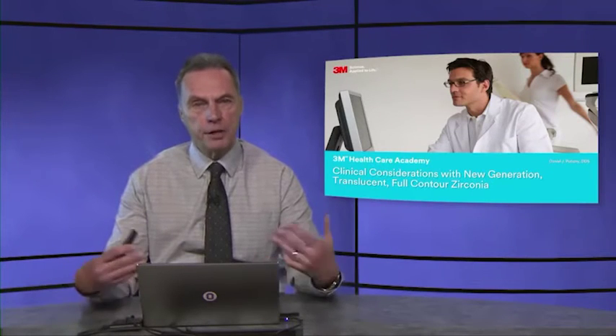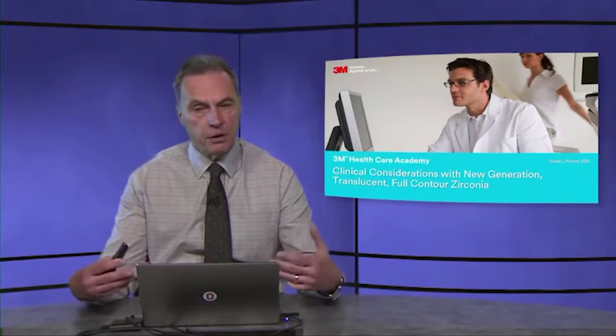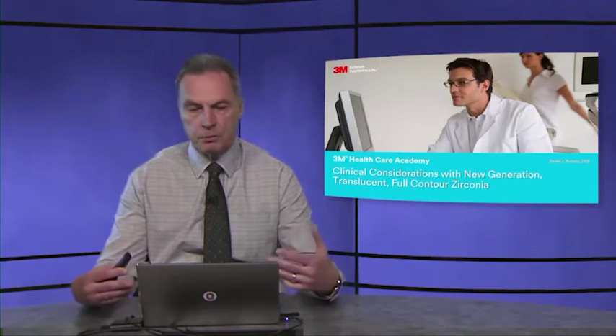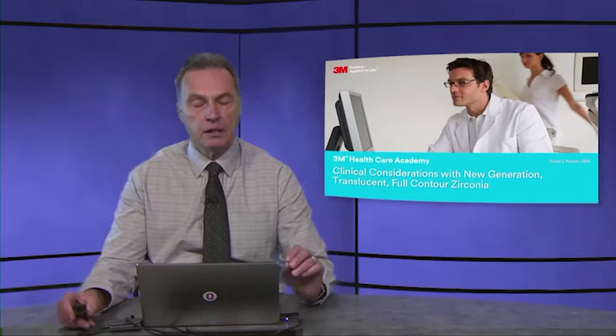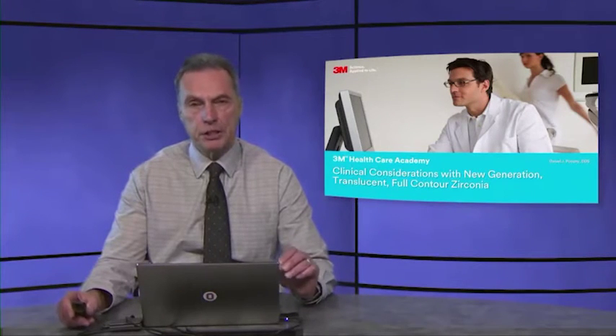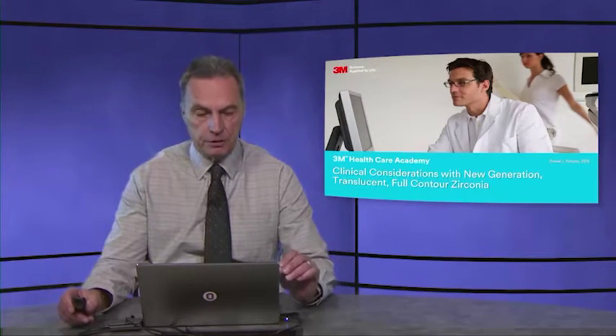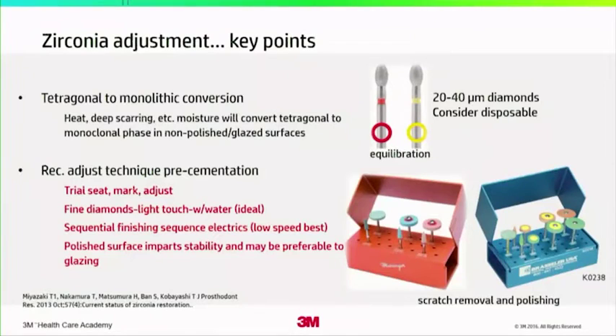So we want to avoid the buildup of a lot of heat. I've done it once or twice with zirconia out of the mouth: if you lean too much on it, with too much pressure, too much torque, too much speed, you're going to heat the zirconia up in a very small area. This will change the phase of zirconia irretrievably, and this is something you want to avoid. Now, when adjusting zirconia, my recommendation is that we use diamond instruments, and I prefer clean diamond instruments.